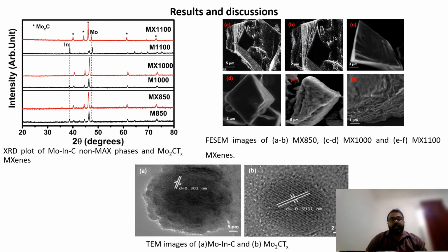The structural characterization of the synthesized MXene and MAX phases was done using XRD, and in XRD we observed that selective etching of indium is happening, with the absence of the indium peak in the XRD plot of the MXene samples. As we can see in the XRD spectrum, the red plots correspond to the MXene samples and the black plots correspond to the MAX phases. We can see in the black plots the presence of sharp indium peaks, which are absent for the MXene samples, which confirms the formation of MXenes.